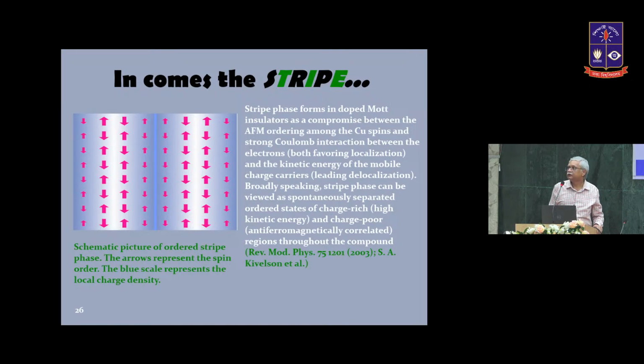And what we do, we make a prediction. We thought if that is the case, there must be a correspondence between spin charge ordering temperature and isotope exponent. Because if the isotope exponent I get is mainly connected with charge and spin density wave, then anything that enhances or destroys the charge density wave or spin density wave order, that effect will be reflected in the oxygen isotope effect. And we have checked the literature, and this is what we get, and to me, this is very exciting because this is what we have found.